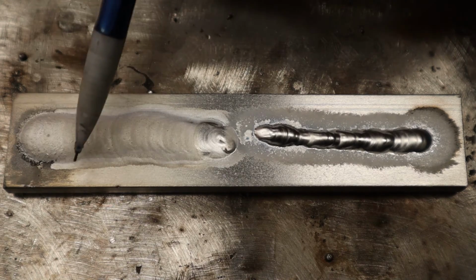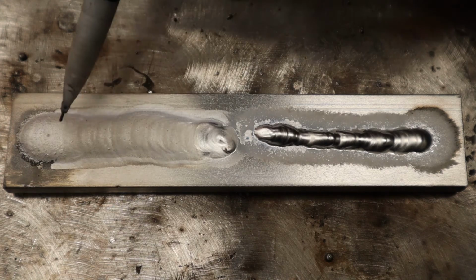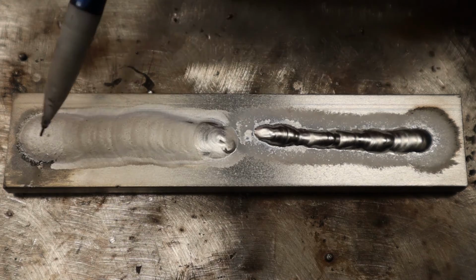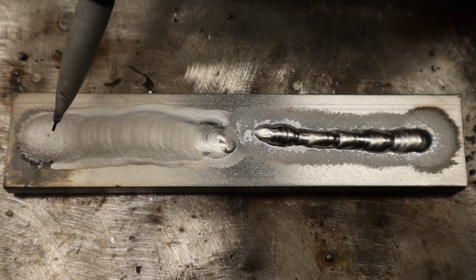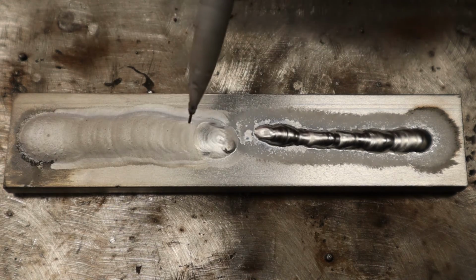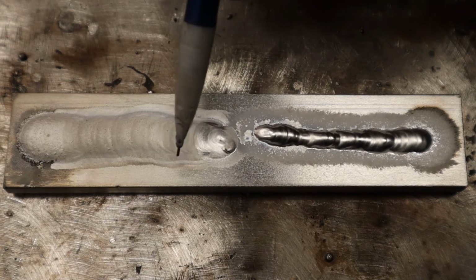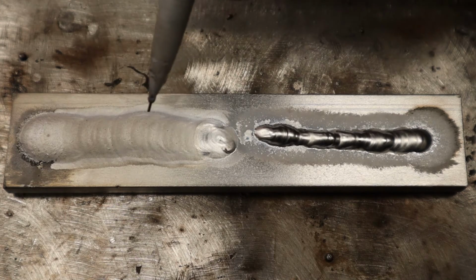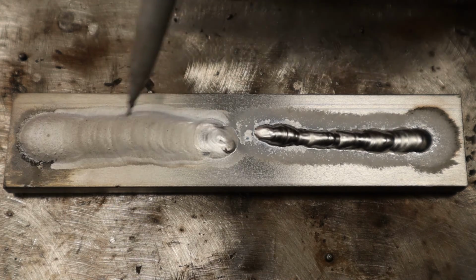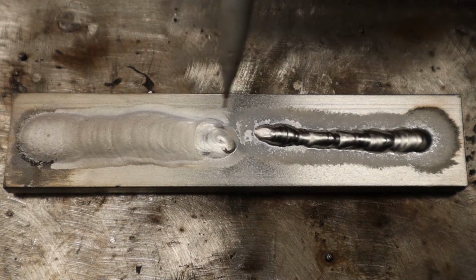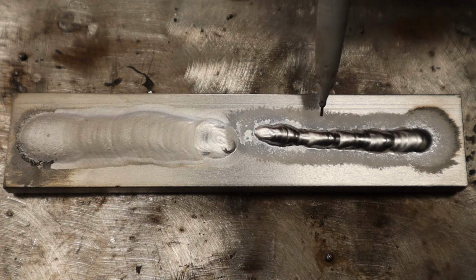And in the beginning here, it's a little wider than in the middle because there is simply less material to dissipate the heat at the beginning of the edge. And then when you get near the middle, there was more. Another thing you'll notice is it has this kind of grayed out look to it. This is the aluminum oxides that are forming on the material because it's too hot. Now when we compare this to the too cold, it looks like that cleaning action has gotten bigger, but it hasn't.